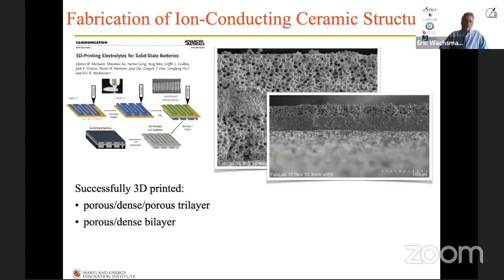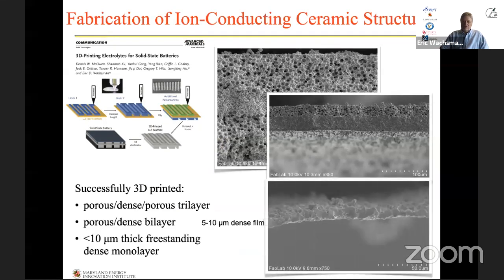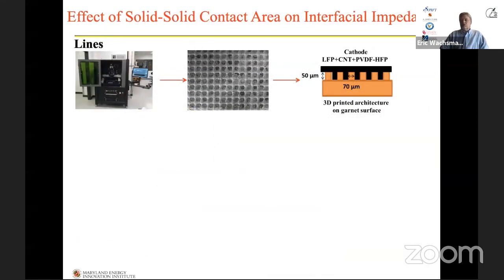We also make bilayers, where again, we have a thin, dense film that's supported on a porous layer. And we've even been able to make self-supporting dense films on the order of about 5 to 10 microns using these types of materials. However, most of our work has been towards making electrode structures. So we want a dense layer for the center of this thing, but we want to control the architecture on the different electrode surfaces. And so we make a number of different structures.